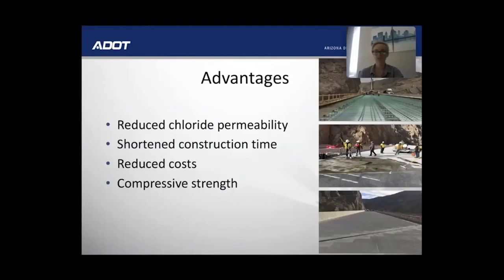So the construction and testing of the silica fume bridge decks have identified some definite advantages towards the use of silica fume concrete. The following list is just some of the advantages identified with using silica fume in the placement of monolithic bridge decks. First, it reduces chloride permeability. This is one of the biggest advantages of using silica fume concrete, which is the refined pore structure of the mortar. As Nye mentioned, this dense matrix really reduces the ability of chloride ions to penetrate the concrete and corrode the reinforcing steel. Also, shortened construction time.